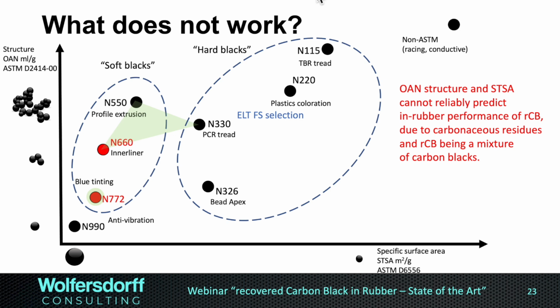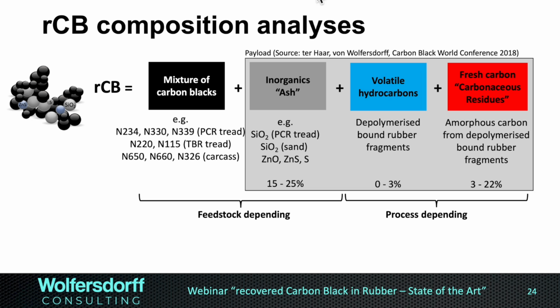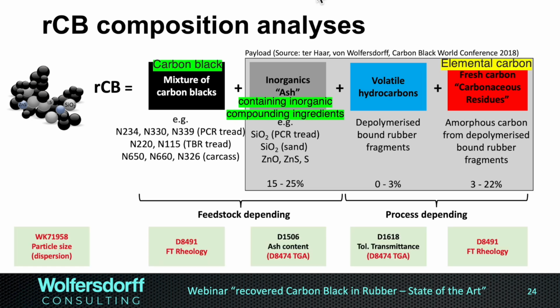And then people say, oh yeah, we're close to a N330. We should be able to replace N330 in a rubber. But that is the misconception. Then the rubber performance is either, if it is like a second grade recovered carbon black, close to a N700. If it is a better type of recovered carbon black, it's close to an N660 carbon black, which is also used in tires. So let's look at composition again and the test methods, which could be important.